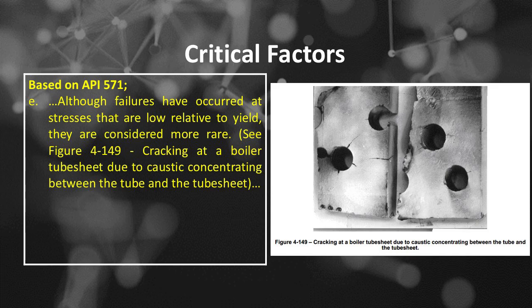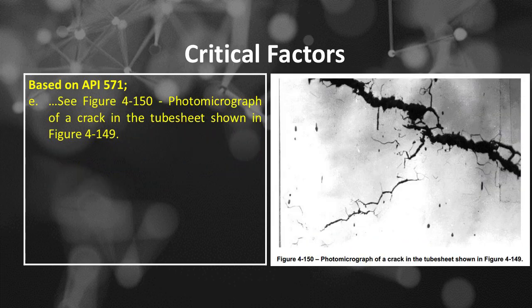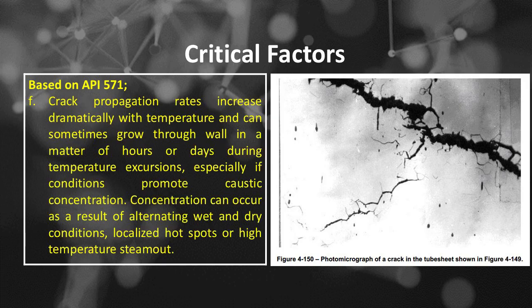See Figure 4-149, cracking at a boiler tube sheet due to caustic concentrating between the tube and the tube sheet. See Figure 4-150, photomicrograph of a crack in the tube sheet shown in Figure 4-149. Number F, crack propagation rates increase dramatically with temperature and can sometimes grow through wall in a matter of hours or days during temperature excursions, especially if conditions promote caustic concentration. Concentration can occur as a result of alternating wet and dry conditions, localized hot spots or high-temperature steam out.